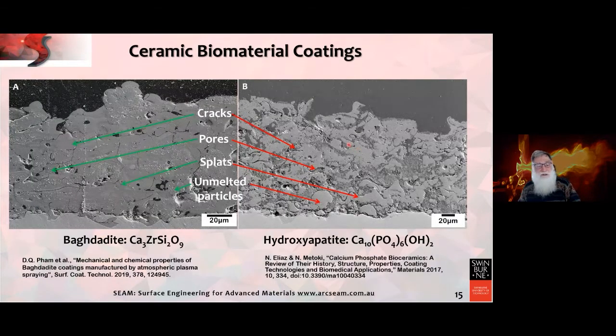Here's another example of a biomaterial, either hydroxyapatite, or within our lab at Swinburne, Pham, the student, soon to be a doctor, almost Dr. Pham, is creating Baghdadite coatings in collaboration with the University of Sydney. And again, we see a roughened surface, we see cracks, we see pores, we see splats, and we see unmelted particles on the roughened substrate. At first sight, you might say that these are ugly, but remember the ugly duckling. These are actually quite beautiful because these are used, at least the ones with hydroxyapatite, currently on orthopedic implants. And these, which are now being explored with very good results, by the way, will replace eventually, in my opinion, these materials called hydroxyapatite.